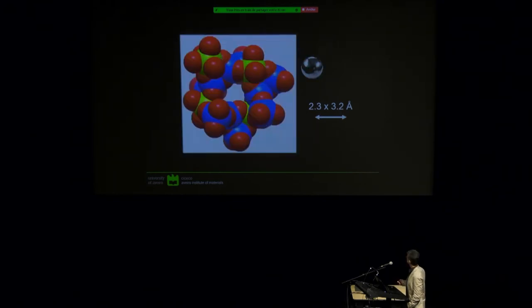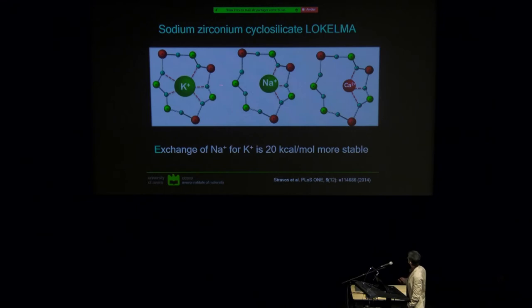So if you cut away in order to see the pores, the small pores, that's what you get. And if that's a potassium ion, it fits perfectly well into the pore. Of course, real life is much more complicated. The structure has a little bit of flexibility, but that's how it works. And so if you compare this hole when it's filled with potassium to the situation where you have sodium and calcium, then you see why it works so well. And so exchange of sodium for potassium is about 20 kilocalories per mole more stable.